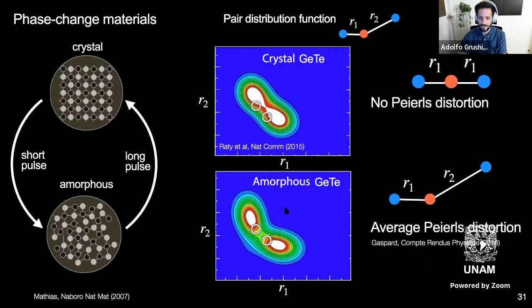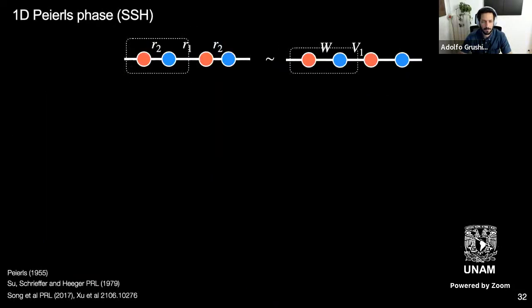And in fact, if you let it evolve, meaning amorphous systems can actually change over time, and in this case they do, you'll find that there's an average Peierls distortion, meaning the two distances are no longer equal. And if you have attended any topological matter course or read books about it, you'll see that this actually reminds you of a 1D example of a topological phase, which is the SSH chain. It's a model for polyacetylene, but let's forget about that. Essentially, you have a chain with two types of atoms, and the two types are there because the distances between them are different.